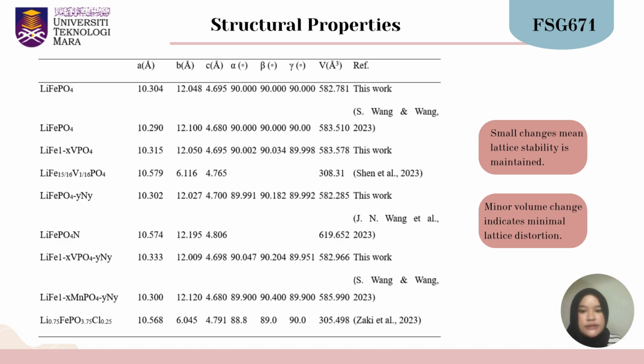Now we continue with the results and discussion section, which highlights the key outcomes of the structural, electronic, and lithium-ion migration analysis. Now let's look at the structural properties of LiFePO4 and its doped variants. As shown in the table, the unit cell lengths along the crystal axes for pure LiFePO4 are a = 10.304 Angstrom, b = 12.048, and c = 4.695 in this work. These values closely match previous studies such as the parameters reported by Wang and Wang. This alignment confirms the accuracy and reliability of our results.